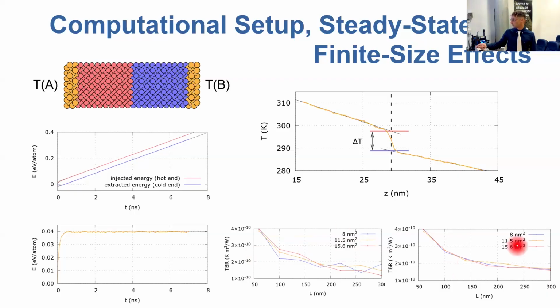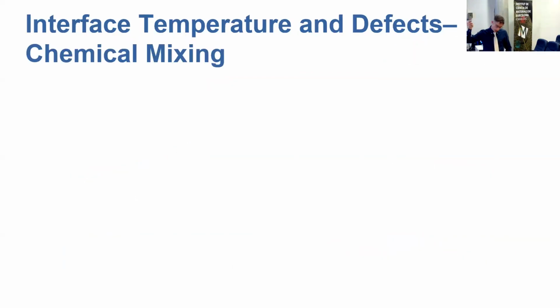And from the two plots, you can also see that 180 nanometers was already providing us with a pretty fair degree of accuracy in order to claim that our simulations were related to the infinitely extended system. So we picked this geometry and we moved on studying the dependency of the TBR on other quantities like the interface temperature and possible defects that can be found in nature, like, for example, chemical mixing.